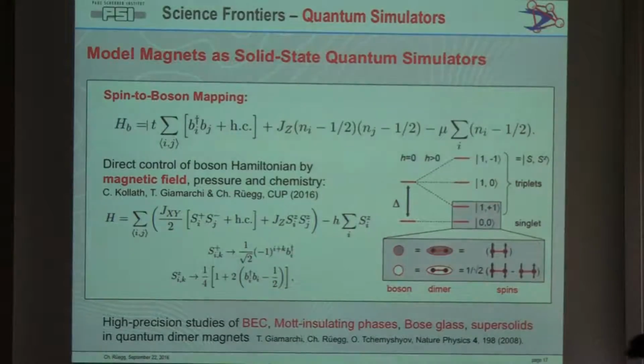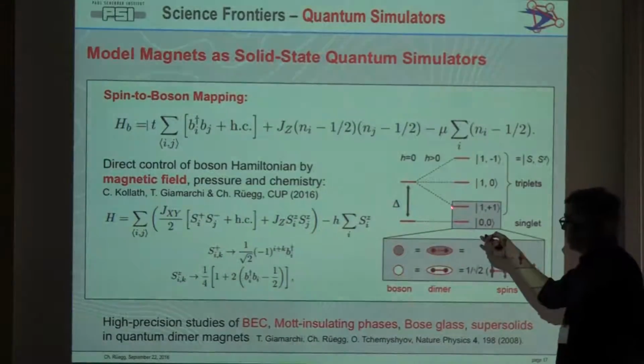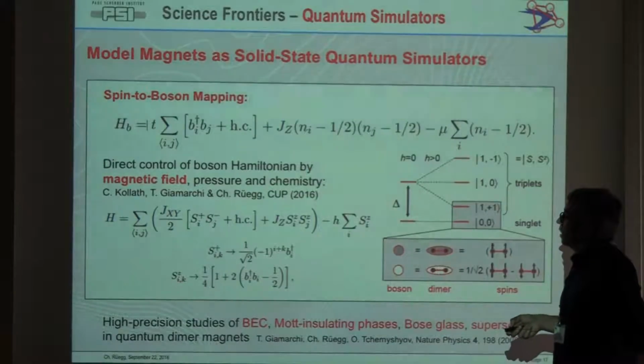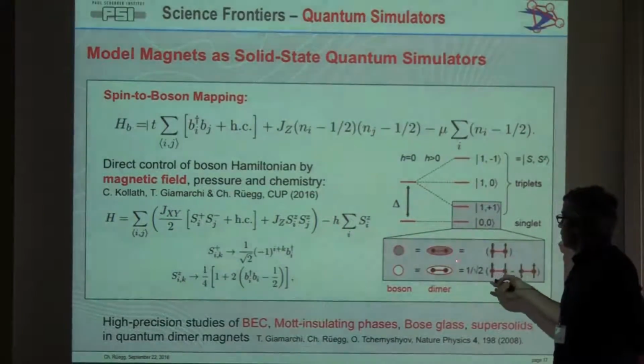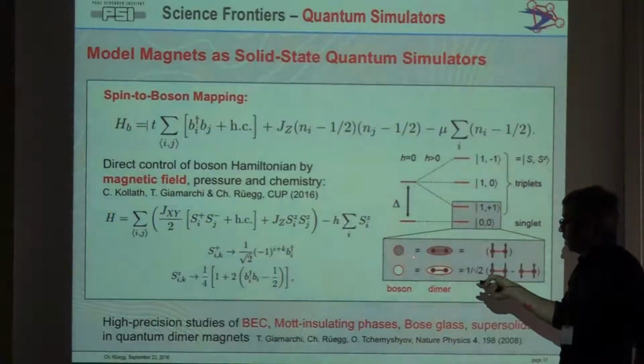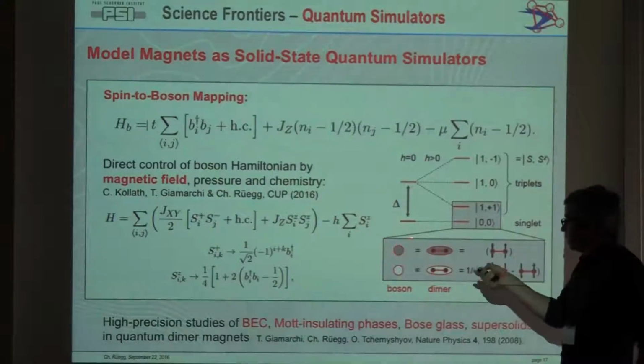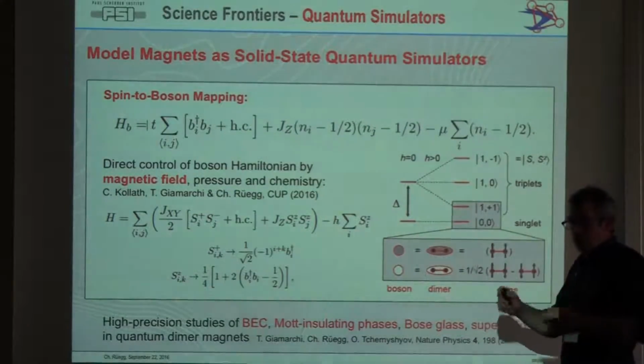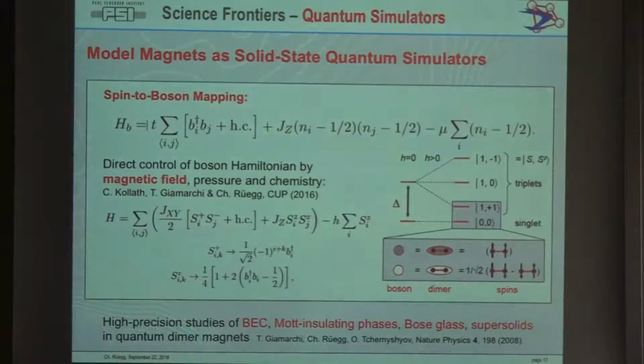Once you apply a magnetic field, you start to Zeeman split, and now the action really starts at the point where you have the intersection of these two low-energy levels. That's exactly where things start to be very interesting. The ground state then acquires a finite population of these triplet states, and then you can start to engineer your states in a very interesting way.